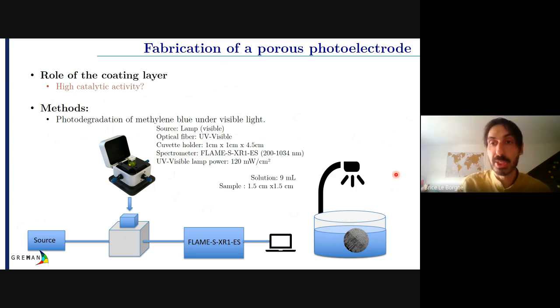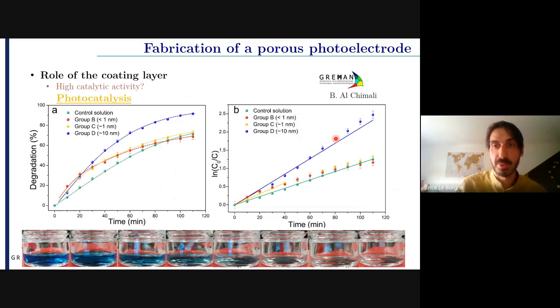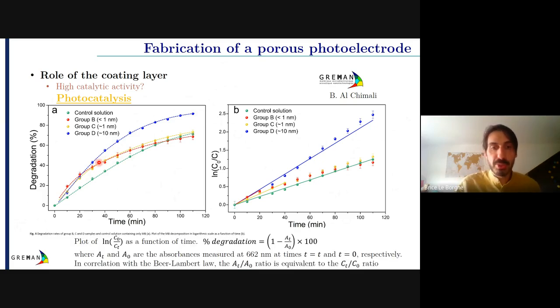So we exposed our sample to a UV visible lamp, and we performed the measurement every 10 minutes. So you can see here it's a bit more visible. At the beginning you have this methylene blue. You can see the porous silicon sample there, and after some point, like 2 hours, you already have more than 80% degradation of methylene blue when you have the thicker layer of titanium dioxide. And when you have the thinnest layers, you can also have degradation compared to the control solution, which is when you just use methylene blue without any catalyst, right? It naturally degrades, but of course, thanks to titanium dioxide and porous silicon, we were able to show that it degrades faster with that.